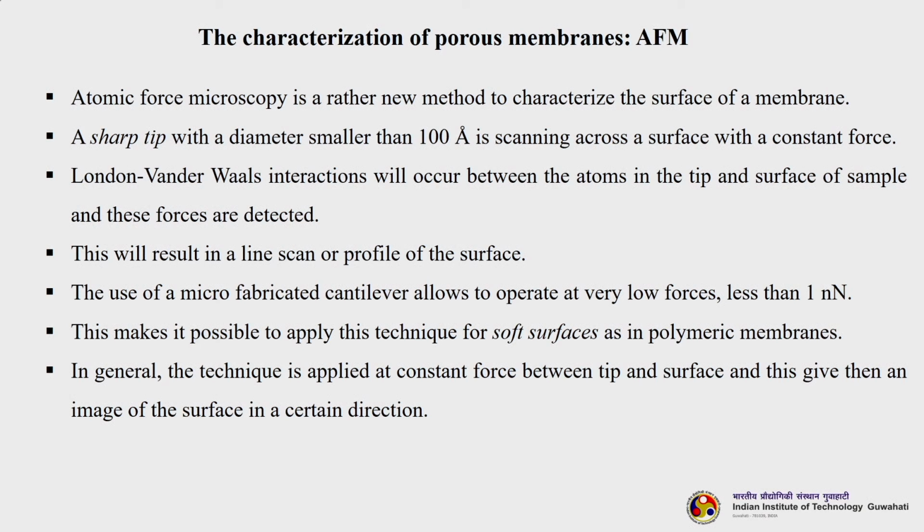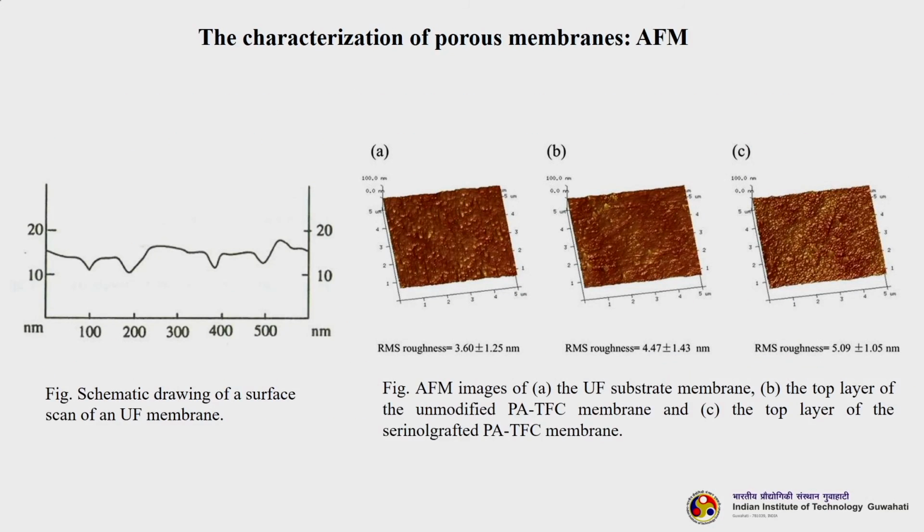So, this will result in a line scan profile. The use of a microfabricated cantilever allows operation at very low forces, less than 1 nanonewton. This makes it possible to apply this technique to soft surfaces, as in polymeric membranes. In general, this technique is applied at constant force between tip and surface, and this then gives an image of the surface in a certain direction. So, let us look at the AFM images.